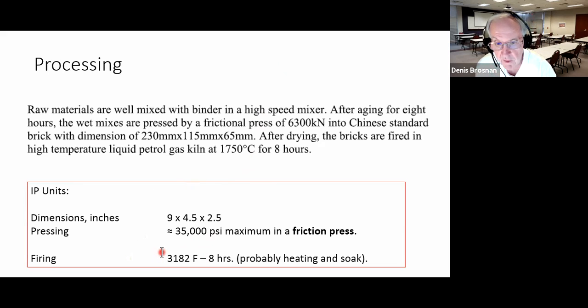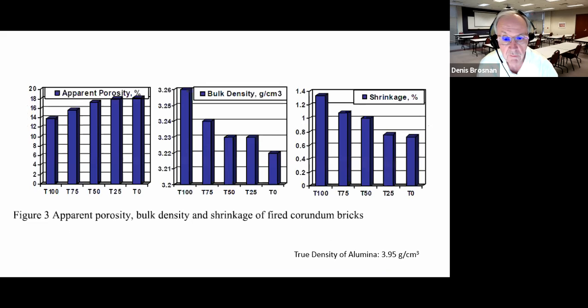And then they said they fired at 1750 for 8 hours. So it's a little bit unclear exactly what they did, but 8 hours was probably the total firing time, meaning from room temperature up to 1750, which would take a few hours, maybe 3 or 4, and then the balance of time at the soak temperature, and probably the kiln was allowed to cool naturally at that point in time. So that was their processing situation. Now we're going to look at some of their data.